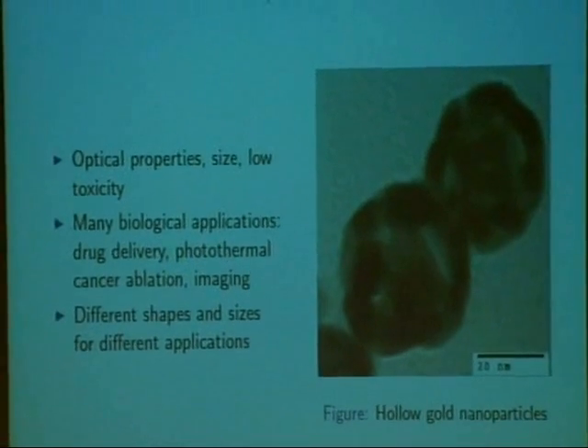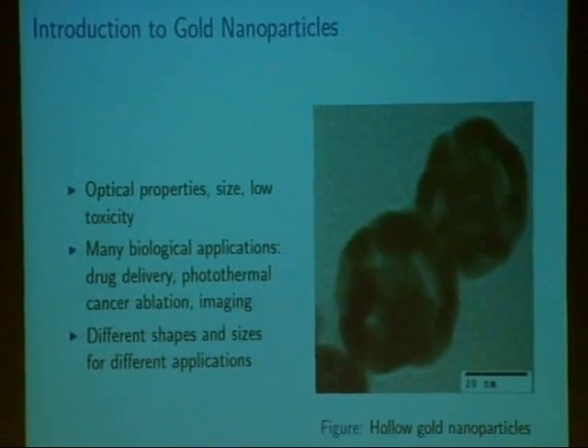Naturally, different sizes and shapes of gold nanoparticles are more well-suited to different tasks. For example, you wouldn't want to coat a glass surface with gold nanospheres — maybe you'd rather use gold nanotriangles or nanoplates. Many studies focus on hollow gold nanospheres because of their increased surface area, which makes it easier to put a larger number of molecules on the gold surface. These hollow gold nanospheres can also be easily tuned to absorb light at different wavelengths, including wavelengths in the red or near-IR regions.